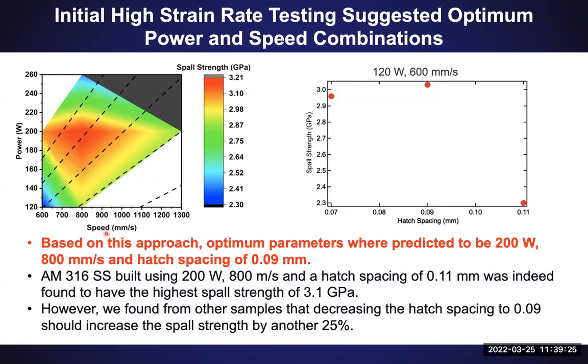In addition to these 2 parameters, we had also changed the hatch spacing. So here I look at Spall Strength as a function of hatch spacing, and you can see that as the hatch spacing is increased, the Spall Strength goes up a little bit, but if you increase the hatch spacing way too much, the Spall Strength went down. So we knew that we wanted a sample that was built at about 200 watt laser power, moving at 800 millimeters per second, and a hatch spacing of 0.09 millimeter if possible.